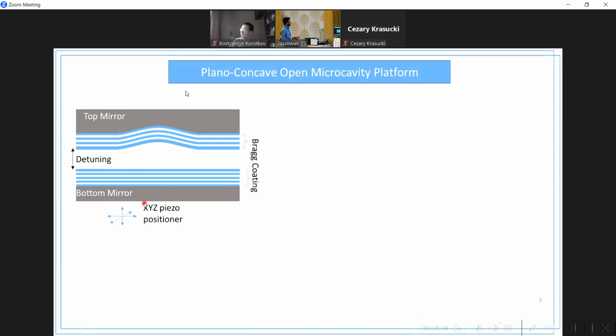And now, if you notice, there is this peculiar concave shape on the top mirror. This plays an important role. If there is an emitter placed inside the cavity, it has a preferential direction to emit into the cavity mode, and the cavity mode in this case is basically Gaussian. As the wavefront propagates, it reaches the top mirror. Since the geometry of the top mirror also follows a Gaussian shape, all of the photons that were going up are reflected back into the cavity mode. This allows us to achieve high Q factors as well as high finesse while maintaining a low mode volume.